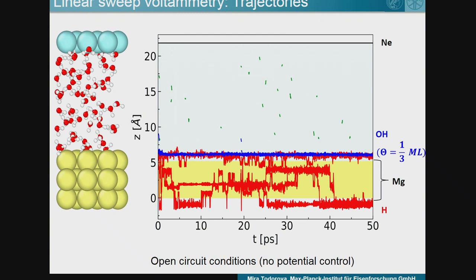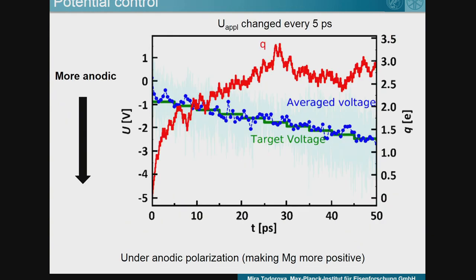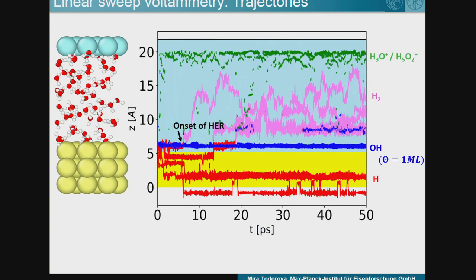Now, what happens when we make magnesium more anodic? So basically, we make the material more positive, and you can see this is our targeted voltage, the instantaneous voltage and the average voltage. One can see that we really nicely follow our targeted voltage, and this is the charge that we need to supply. Now, this is the same picture as the one I showed you before, but now really under anodic polarization, anodically polarized magnesium, and you can see that much more is going on.